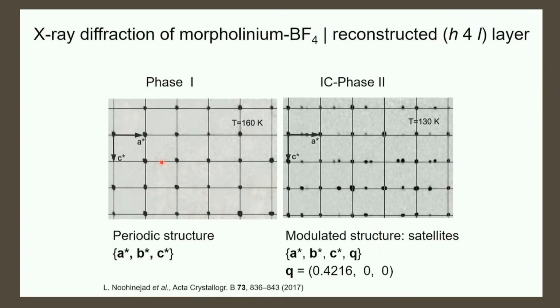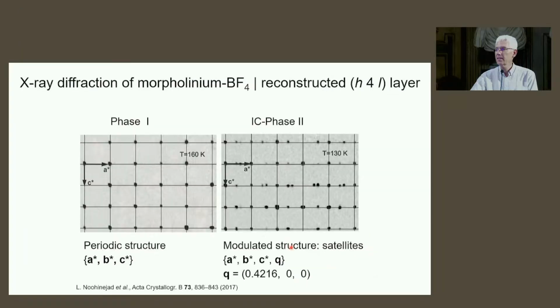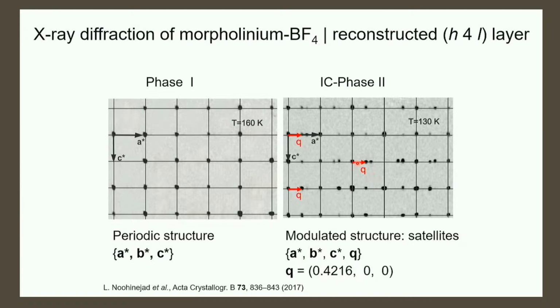So this is an experimental diffraction pattern. That means a reconstructed reciprocal layer from the actual measured frames. This is a periodic structure, and if you cool down this morpholinium tetrafluoroborate, as done by Laila Noohinejad, then at 130 Kelvin you see additional reflections, which are called satellite reflections, and which cannot be indexed with 4 integer indices, but we can index the neighboring main reflections, which are the ones which exist solely at higher temperature. They remain here, and then we can describe these extra spots as a distance q away from such a main Bragg reflection. And this distance q is valid everywhere.